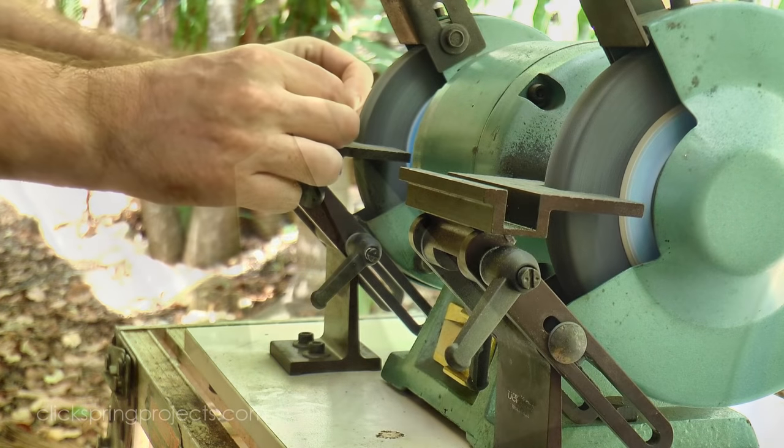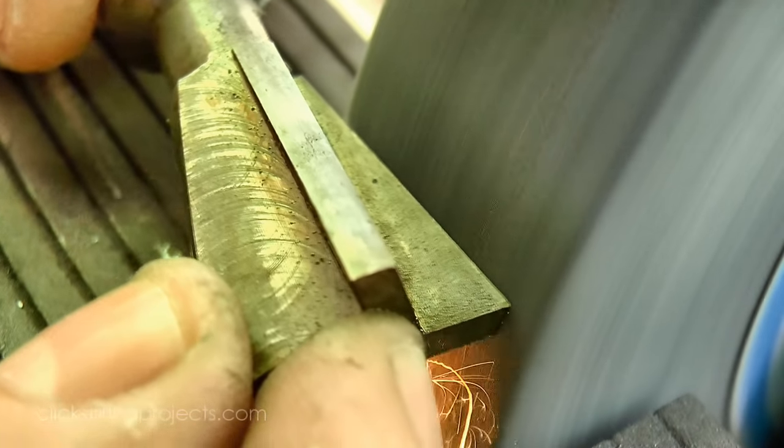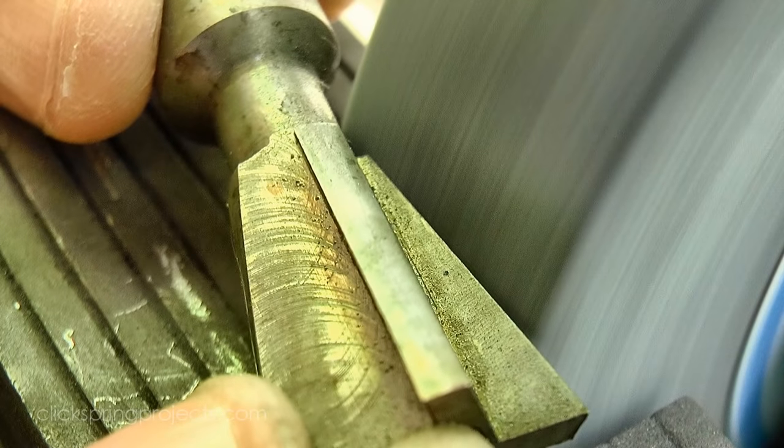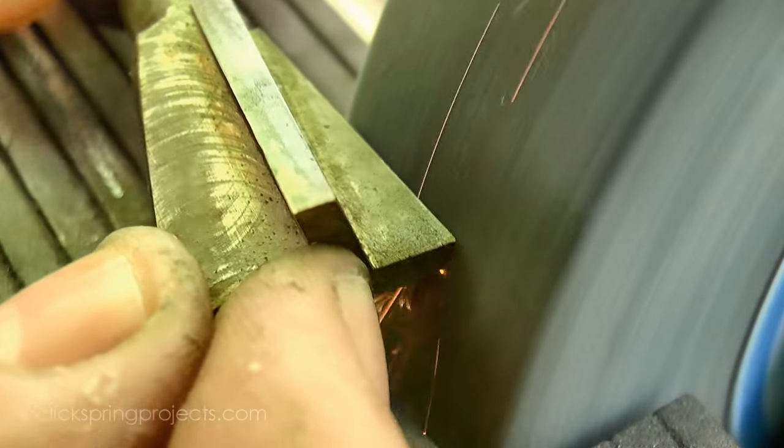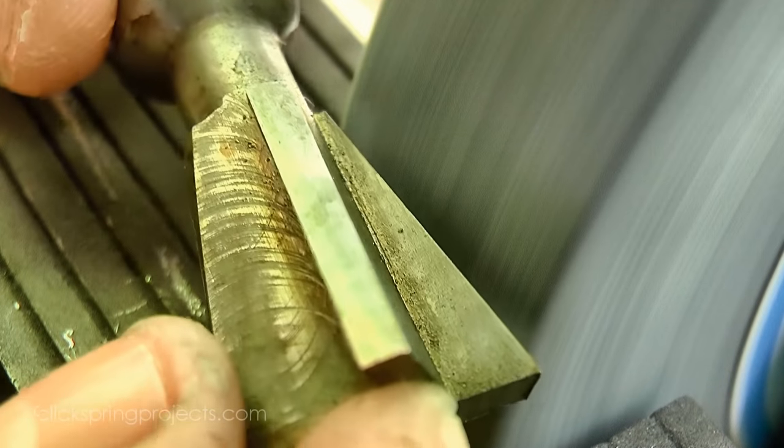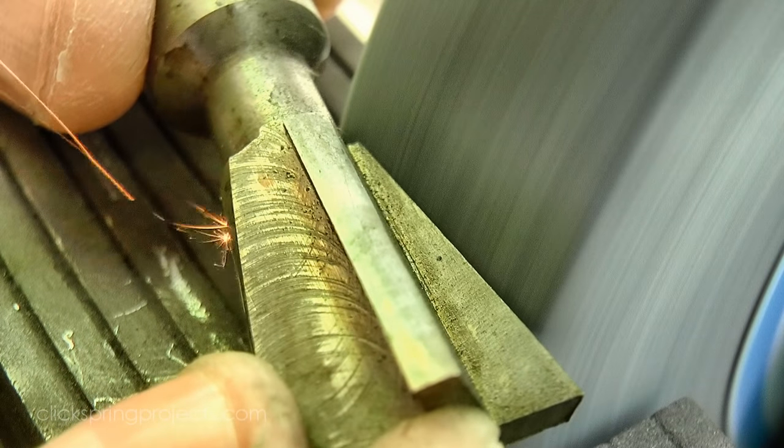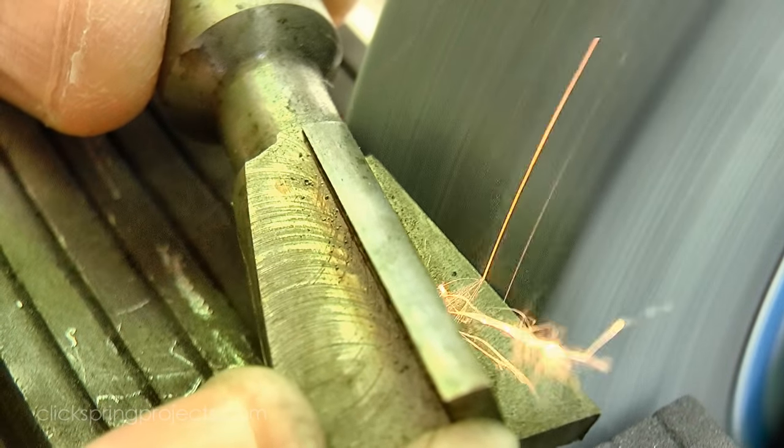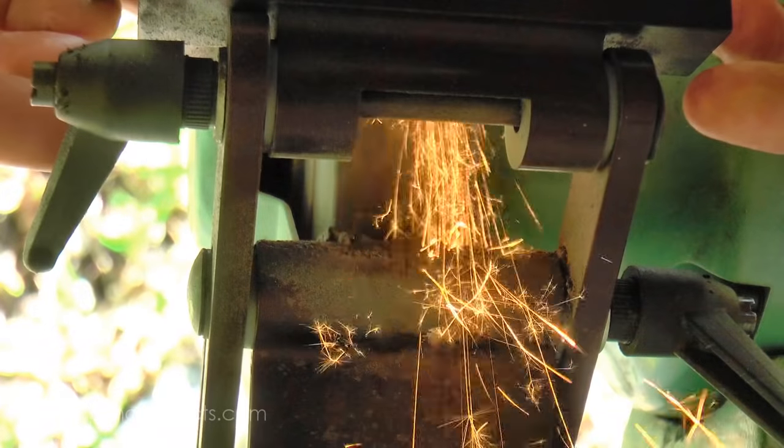Now ideally I'd form the relief angles using a tool cutter grinder, but I don't have one, so I'm freehand grinding them using this bench grinder. I'm keeping the contact with the wheel quite short to keep the heat generated to a minimum. I don't want the temperature to rise so much that it softens those cutting edges.